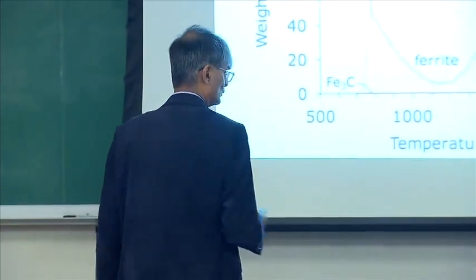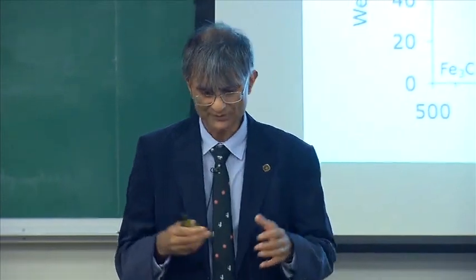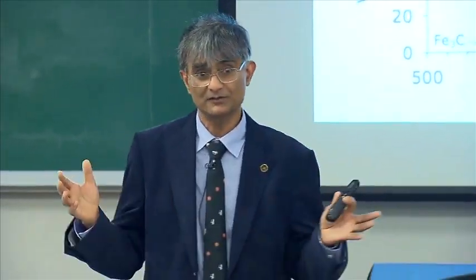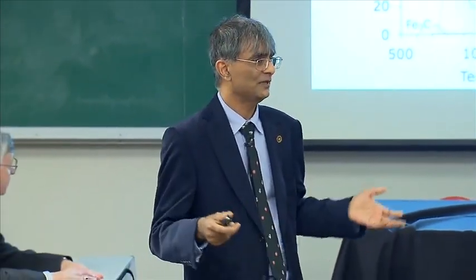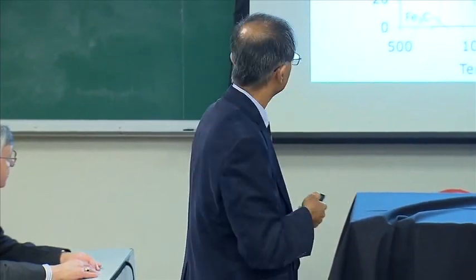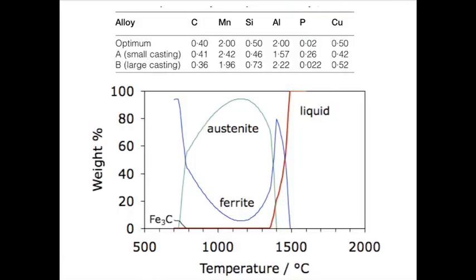Now, the way that you work with mathematical models is that you make some prediction, and there are uncertainties. So you do not make a large quantity of material. You first make about 60 grams of material to validate your prediction. And if it's going roughly in the right direction, you make a larger casting. And of course, when you make these castings, the compositions won't be exactly correct.